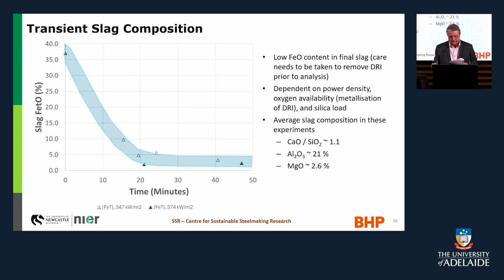Slag compositions. Slag composition is a real challenge in this type of smelting reactor because we've got metallic shot in the slag, we've got FeO in the slag, we've got other iron units there as unmelted DRI. So we've got all these things going on. So if someone says, well, what slag Fe are you running? I say, well, which Fe were you really talking about? So we make this graph, but there are some caveats about what it really means.